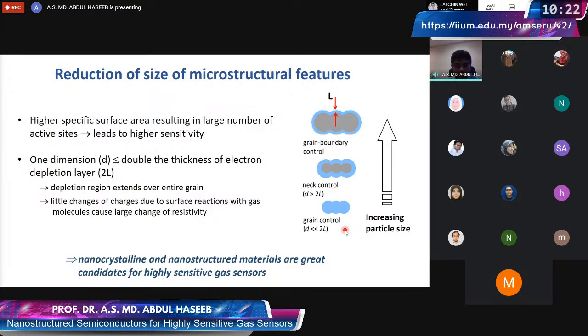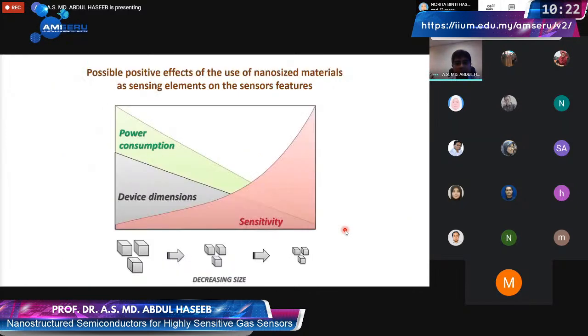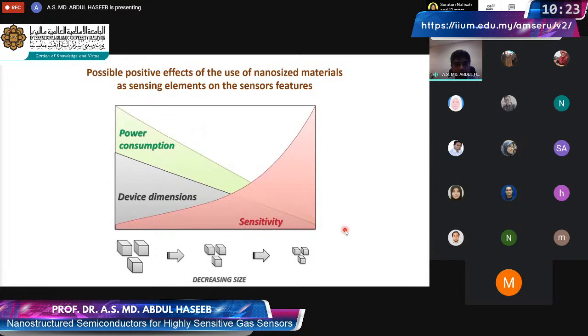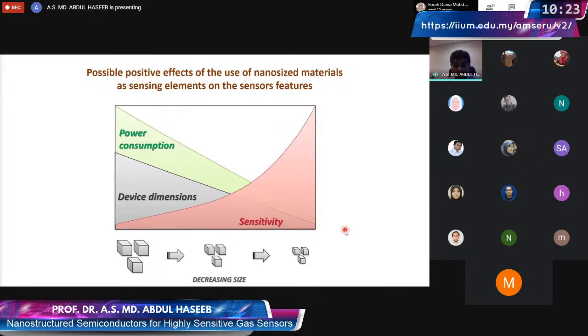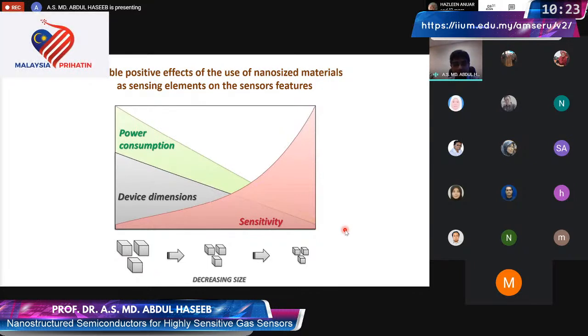And that is why the trend now is to research into the nanocrystalline material or nanostructured material in order to improve the gas sensing performance. And some of the important benefits that we get out of these small crystals or small nanostructured material is that, number one, as I mentioned, the sensitivity increases because we get large signal as most of the material or larger fraction of the materials become active in the reaction. We can reduce the device dimension, which is very important now in technology. Miniaturization is the trend. And power consumption also is reduced. And this is also another very, very important characteristic that we want to have.